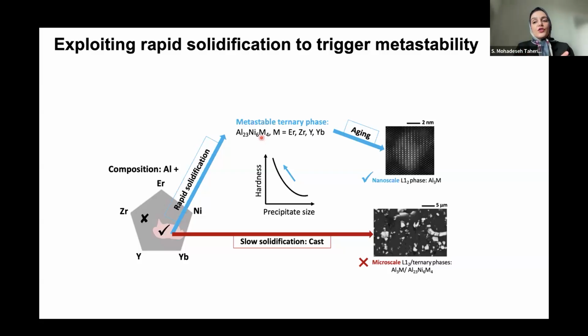That state is very useful because after printing, you can heat the sample or age the sample, and then you will see some features inside the sample that are nanometer scale. If the same composition is cast or slowly solidified, you see these features at the micron scale. You see orders of magnitude difference. And why is it important? Because we know that if these features, which are called precipitates, are smaller, the material becomes stronger.